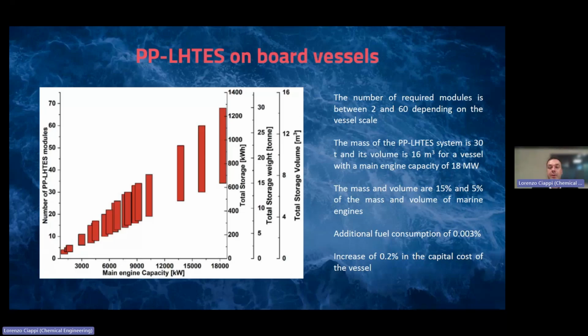Moreover, it was found that the additional fuel consumption of the application on board of the pillow plate latent heat thermal energy storage is close to negligible, and the increase in capital cost of the vessel is 0.2%. This kind of technology can provide a significant effect, as previously seen on the waste heat recovery on board, so its feasibility was positively confirmed.